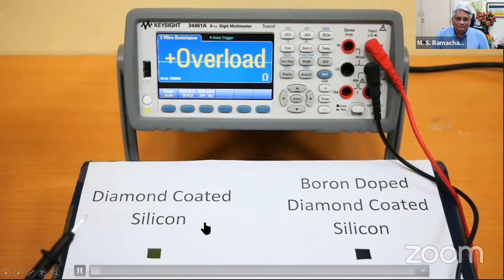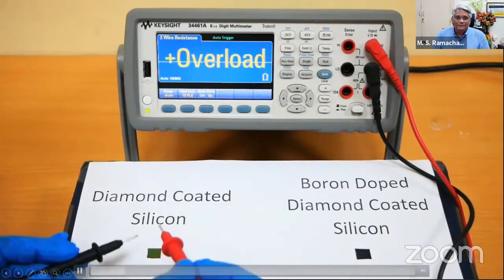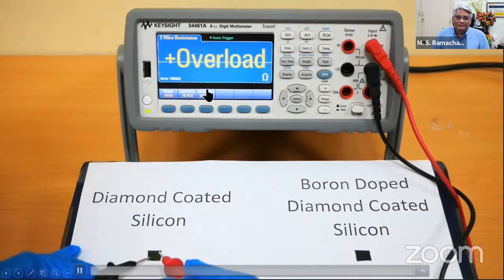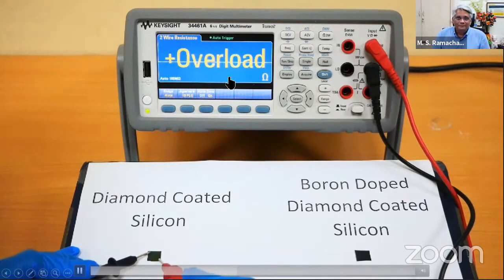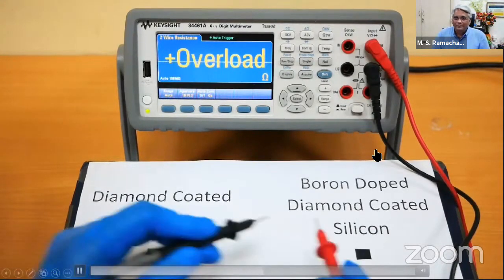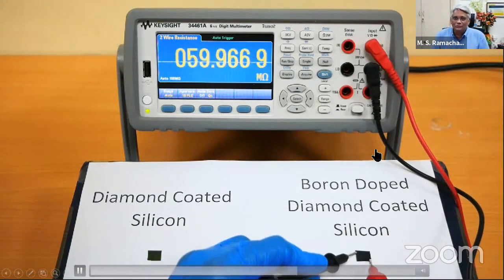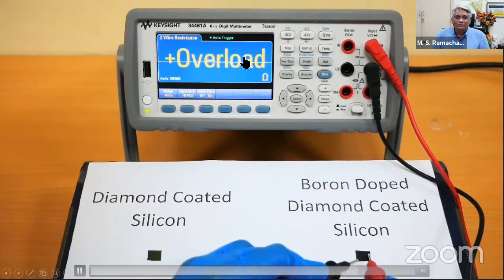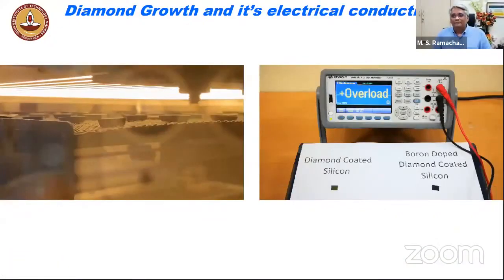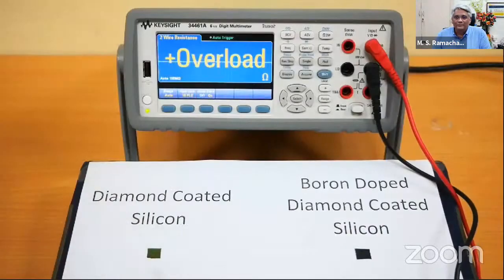The first one is when you just bring those 2 multimeter probes, you see an overload here. That means the resistivity or resistance is very high in gigaohms, right? It's beyond the limit of this meter. But then the moment a small amount of boron is doped in it, 3 to 5 mole%, you see that. So the gigaohm resistance drops down to tens of megaohms. This is really beautiful, right? Because this is the power of doping in a lattice like diamond. Same thing happens in most of the semiconductors also. So the resistance changes significantly with boron doping, right?